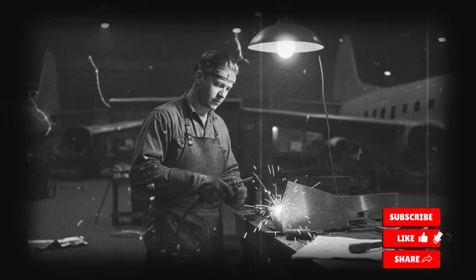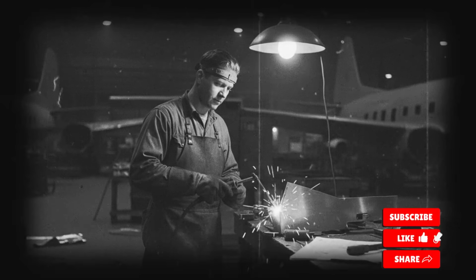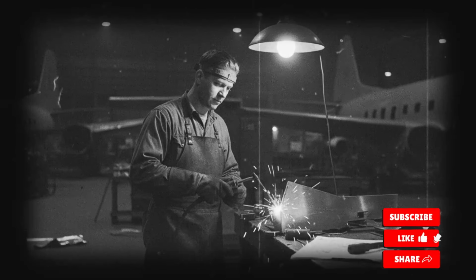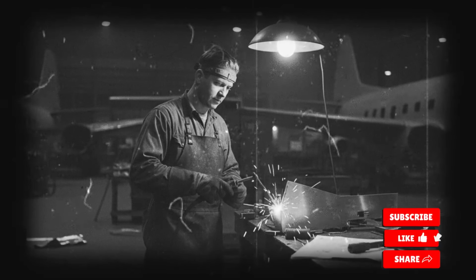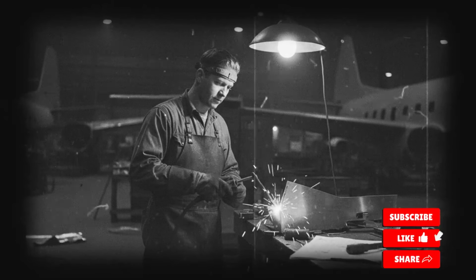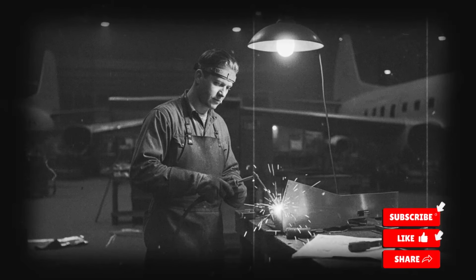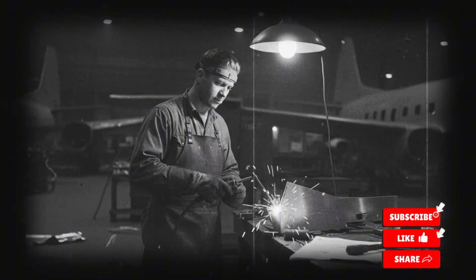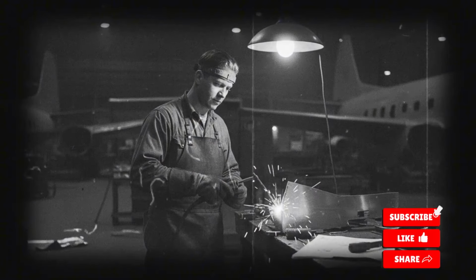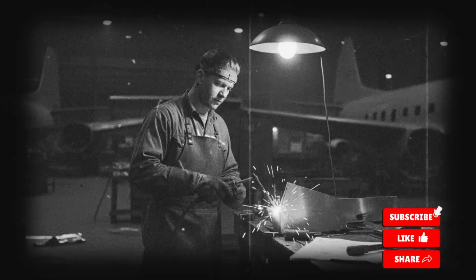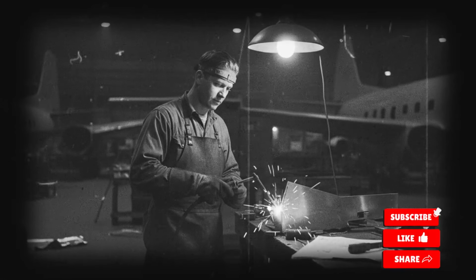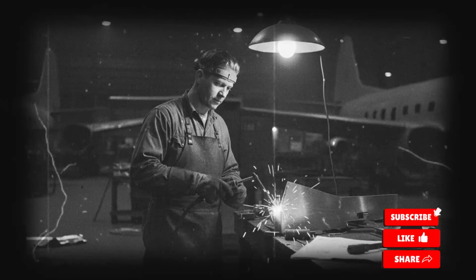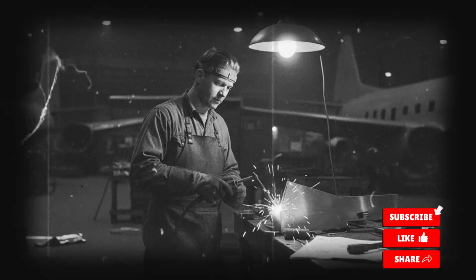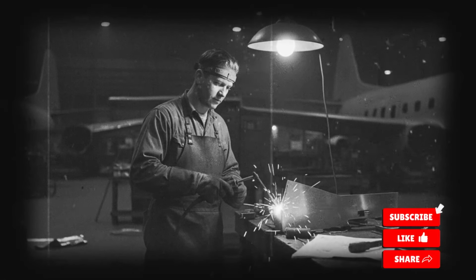Captain Marsh remained skeptical, but the data was undeniable. He authorized flight testing of 3 B-29s with known welded joints. The aircraft were flown to 40,000 feet, well above normal operating altitude. They were subjected to violent maneuvering that imposed loads exceeding design limits. They were pressurized and depressurized repeatedly during flight. Every test was designed to stress the welded joints to failure.